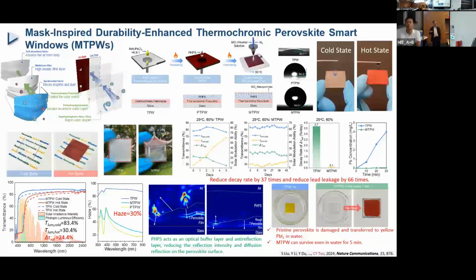So in this way, we can find that this is a cold state, this is a hot state. The transmittance at cold state can still keep at about 80%, hot state at 30%, leading to about 24.4% solar modulation ability. Most importantly, the haze of the window is dramatically reduced.